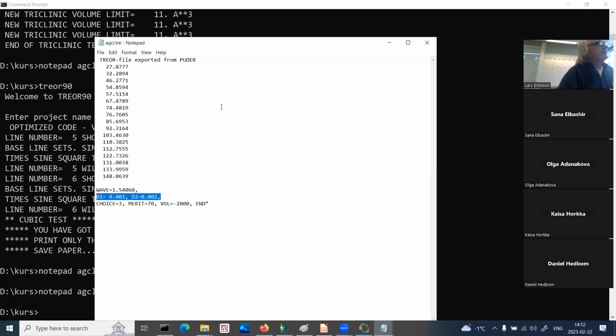Why do you think we had so much problem with the simple cubic pattern? Yeah, silver chloride is a precipitate and I filtered off only a little bit. So I kept it on the filter paper and put the filter paper on the wafer. So I had a quite large systematic error. It's bad data.